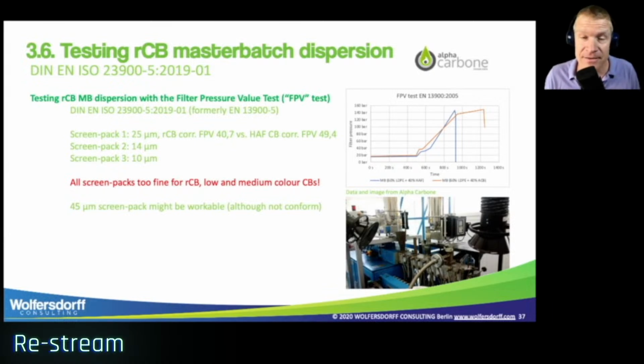Actually, in that filter test, the broadest, the biggest kind of sieve opening is 25 micron, which you can recall from early on is already used for high performance plastics. And then the screen pack 2 is even worse. It's less than that. It's 14 micron. And the screen pack 3 is 10 micron, which is used for synthetic fibers. So perhaps the recommendation here is a 45 micron screen pack is best for the recovered carbon black master batches.